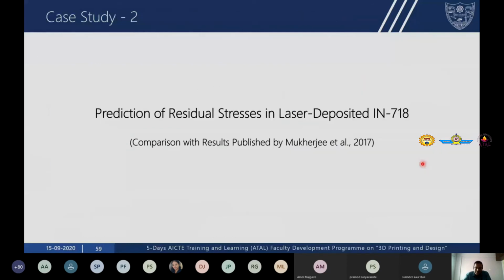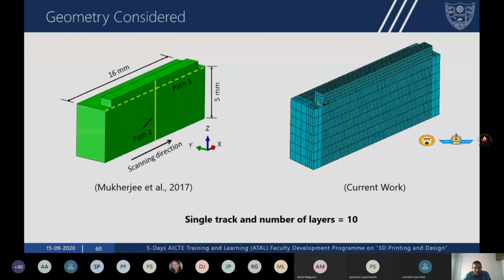Now the second case study that I'm going to present is one we have done in Inconel 718, where we have tried to validate our computational models with existing experimental work published in literature. This is from a 2017 paper. In this paper, they have done the laser metal deposition, or laser direct energy deposition, process, where they deposited 10 layers, single track, on top of a substrate, and we have also simulated the process. This is our model on the right side, and this is the work from the publication.